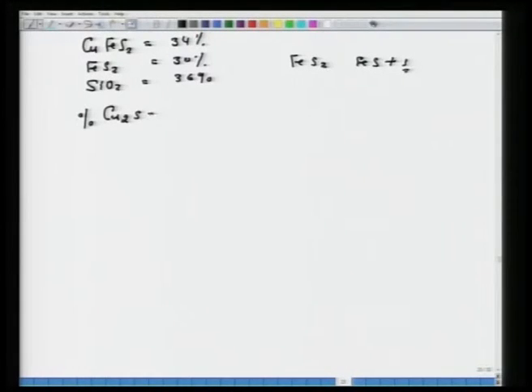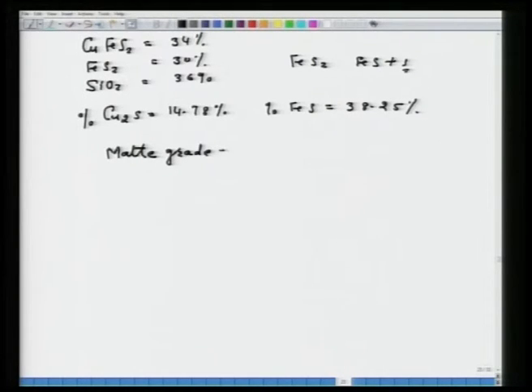So, percent Cu2S will be 14.78% and percent FeS, if you calculate, will come out to be 38.25%. Then the matte grade, as defined, equals percentage copper upon percent Cu2S plus percent FeS, into 100. If you substitute, that will come to 22.2%. So, that is how you will be calculating this particular problem.